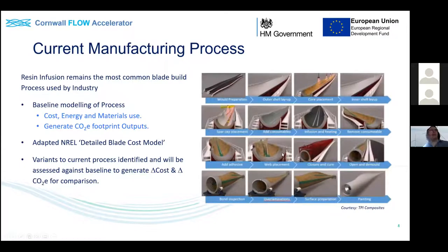So very briefly, obviously, resin infusion remains the dominant mainstay of blade manufacture. And usually it's around a 16-step process as illustrated in the panel on the right, basically consisting of two half shells to produce skins in, which are typically carbon and glass fiber composite, often with an epoxy or a vinyl ester-based matrix being infused. That shell basically, after curing, has the placement of webs. The entire construction is then closed in the assembly for adhesive bonding of the two half shells.